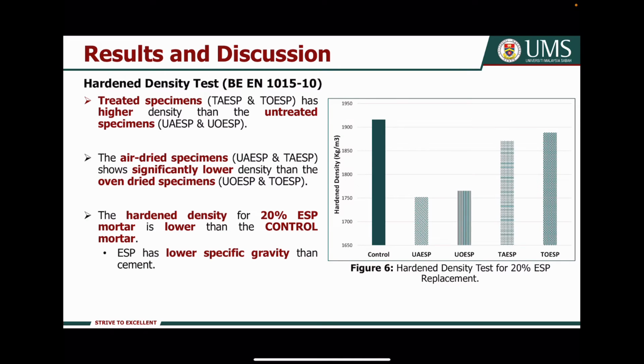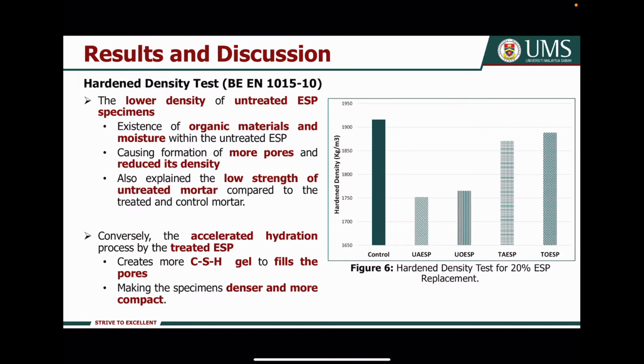On the other hand, the hardened density of the ESP mortar is lower than the control mortar. This is probably due to the lower specific gravity of eggshell powder compared to cement. The lower density of untreated ESP specimens is due to the existence of organic materials and moisture within the eggshell powder. This causes a formation of more pores and reduces its density. This also explains the low strength of untreated mortar compared to the treated and control mortar. Conversely, the accelerated hydration process by the treated ESP has created more CSH gel to fill the pores, making the specimens denser and more compact.